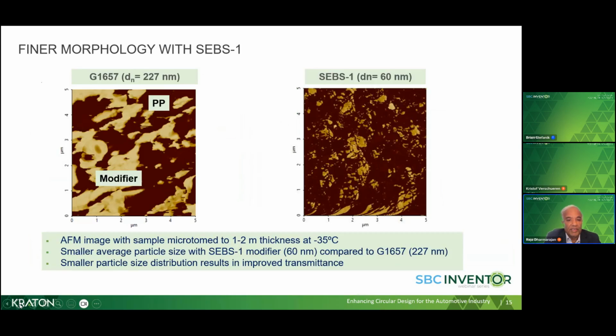So to understand why and how these modifiers work, we actually did some microscopy study, and in this slide, I show you atomic force micrograph or AFM images of the TPO compound. The micrograph on the left-hand side uses our commercial G1657, which is one of our workhorse TPO grades for classical TPO applications. And on the right, we compare that with SEBS1, which is our experimental SEBS grade that we have developed for the semi-transparent application. So the dark phase is the polypropylene matrix. The light phase is the modifier.